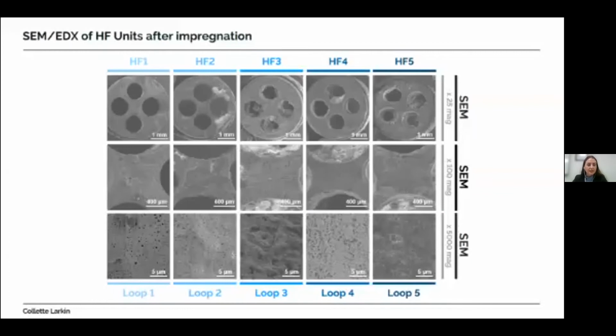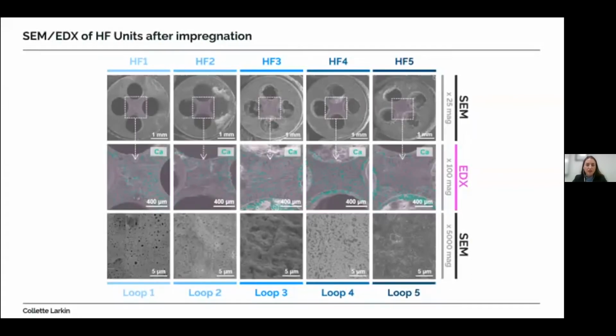And taking an EDX analysis of the hollow fibre adsorption units at a magnification of 100, it can be seen that the calcium atoms are homogeneously distributed and increase in frequency as the number of impregnation loops increased. And then another characterization technique in the form of mercury intrusion porosimetry analysis was conducted, as it shows the empty volume present within the fingers and hence the impact the number of impregnation loops has on the pore size distribution within each of the hollow fibre adsorption units.